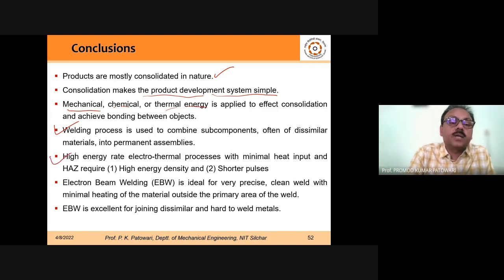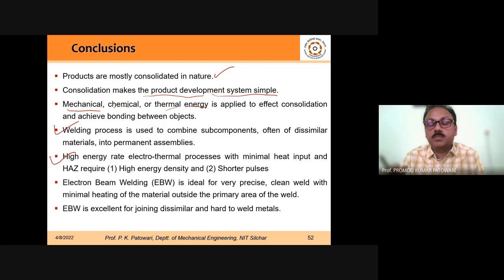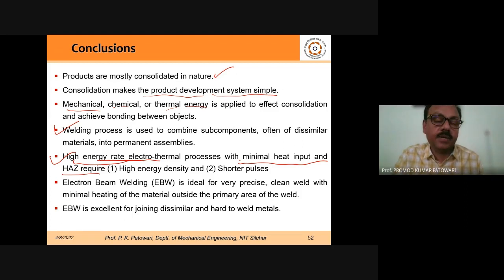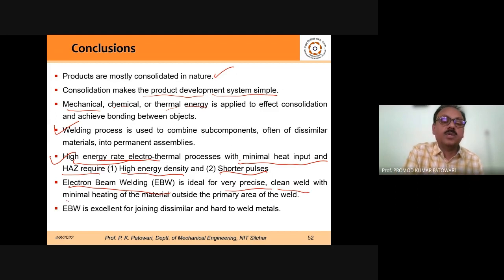And if I look at a very big spectrum of the energy sources, you will find that high energy rate heating will have the minimum heat input and minimum heat affected zone, and that requires these two conditions: high energy density and shorter pulses. So accordingly, I need to find the source which can give me the high energy density and shorter pulses, and that's why we are going for laser welding or electron beam welding. So electron beam welding is one of the ideal processes for very precise, clean welds with minimum heat affected zone. And EBW is one of the excellent ones.